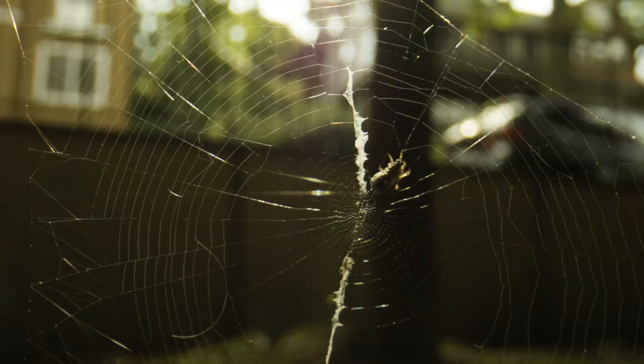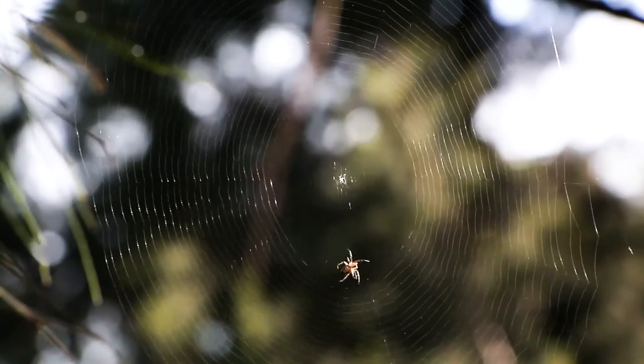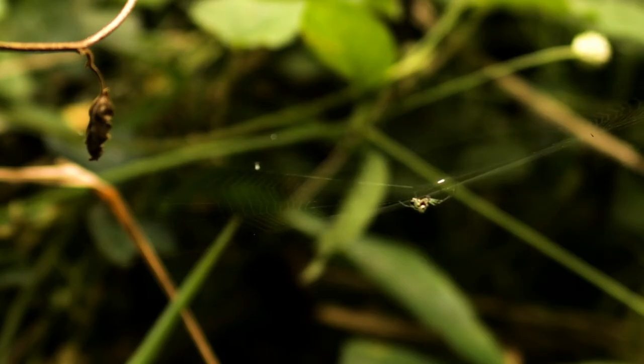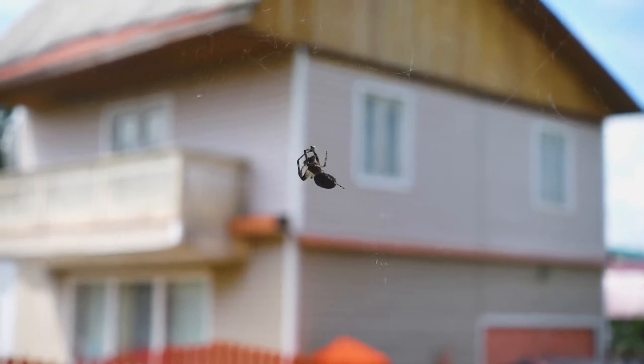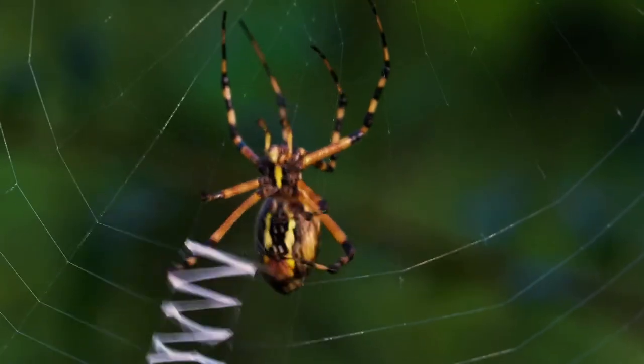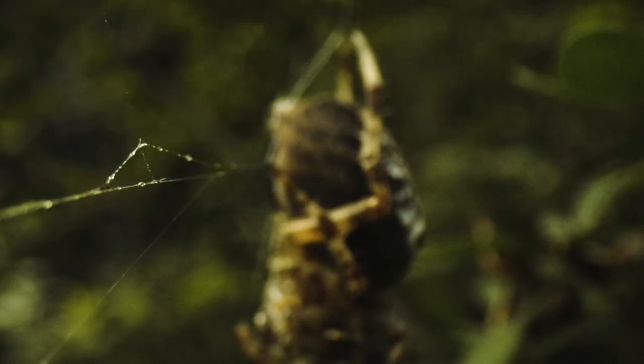When you think about why a spider might make so many different kinds of silk, it really comes down to function. The frame and radii need to be stiff to support the web. But if a web was made entirely of strong and stiff fibers, it might be a lot easier for an insect to just bounce off. So capture spirals stretch, absorbing the impact of that insect, and the little gluey droplets stick to the insect's body, holding it in place and giving the spider time to catch prey. Egg case silk, dragline silk, capture spiral silk, and prey wrapping silk all have different functions and different material properties.